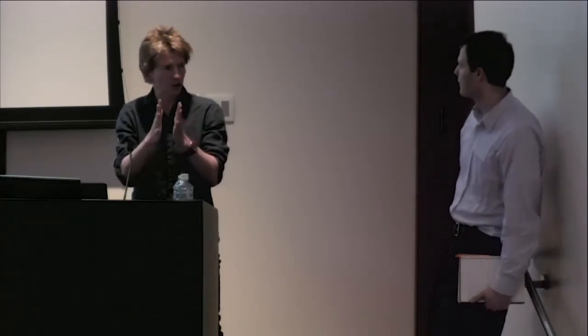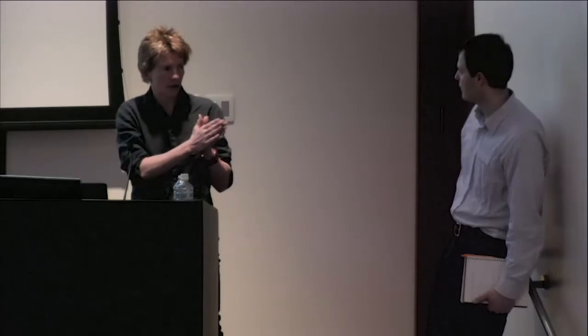And then the other thing which is really interesting about the beta phase would be that if you could introduce, rather than the 5 or 10% of beta phase that we could do, 50%, you could have something really speedy. But it would then depend on exactly the thing you said, which is how good is the coupling between the two. And I think there's not enough evidence to really answer it, but we don't see the trap-free mobility getting better with beta. It gets worse. Last question over here.